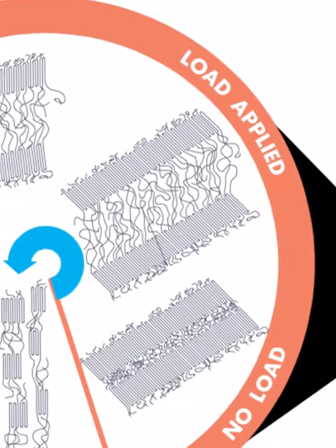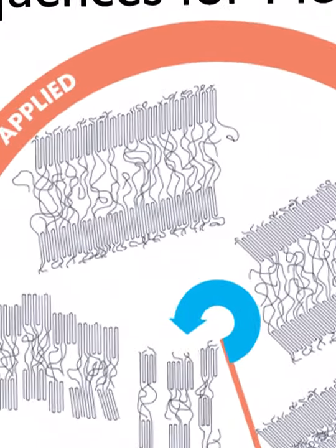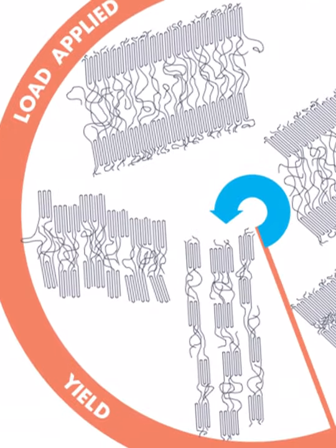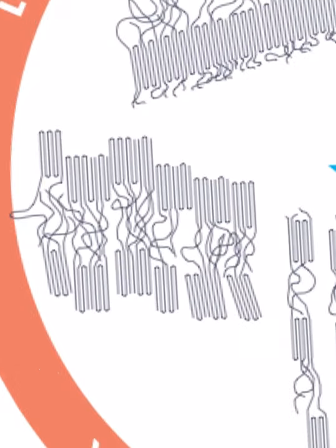And so you start stretching out the amorphous component, and you keep increasing the load, and you stretch that amorphous component out some more, and then at some point that amorphous component becomes so stretched that it starts pulling on the crystal structure, because that's the strong chain direction as it goes in and out of that crystal structure. And when it does that, it starts to fracture those crystals. Okay? And the material in between these fractured areas essentially melts, quote unquote. It goes from being crystalline to amorphous. It has to, in order for this process of sliding to occur. Okay? Does that make sense?